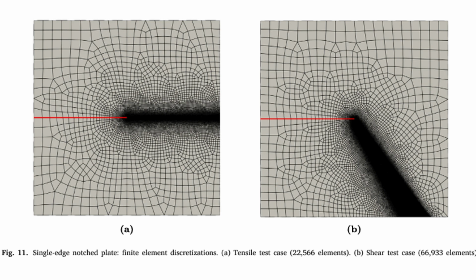And that's why AM was invented for this. It avoids getting lost in that complex landscape by breaking it down. Fix the crack state, solve the easier convex problem for the material's displacement, then fix the displacement and solve the easier convex problem for the crack state. Back and forth. Sequentially solving simpler problems makes sense why it's robust.